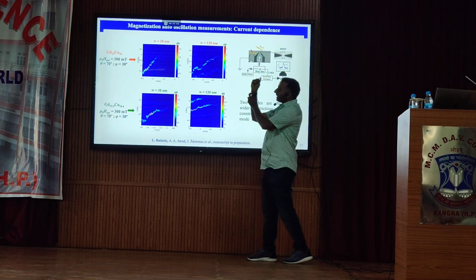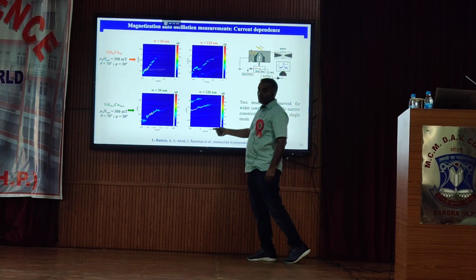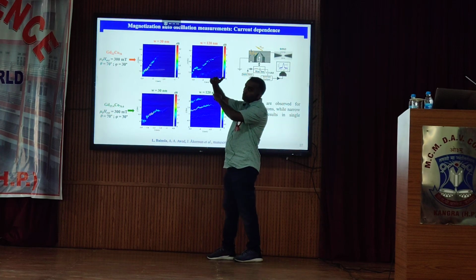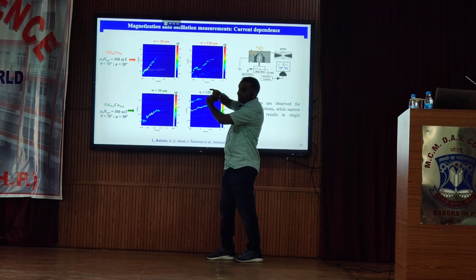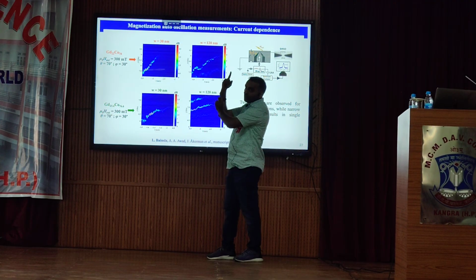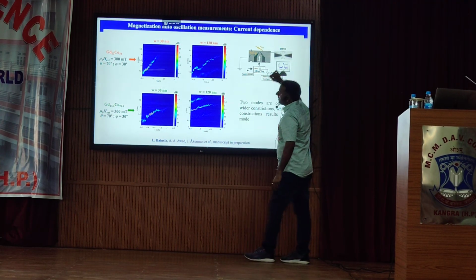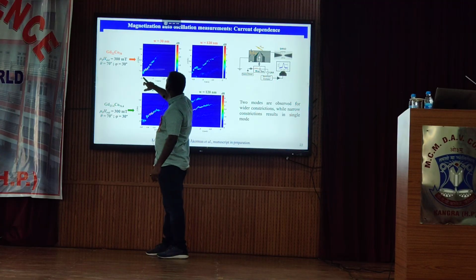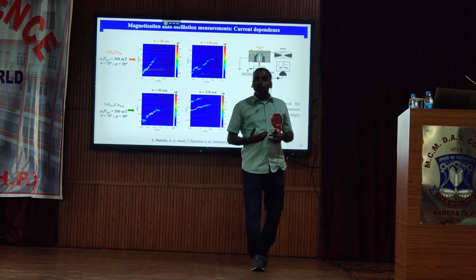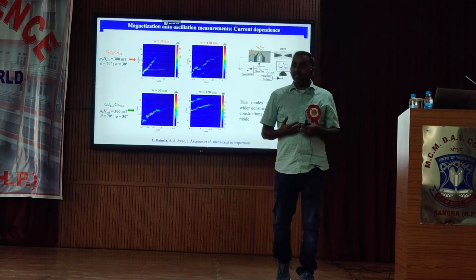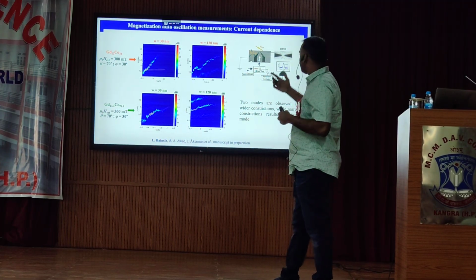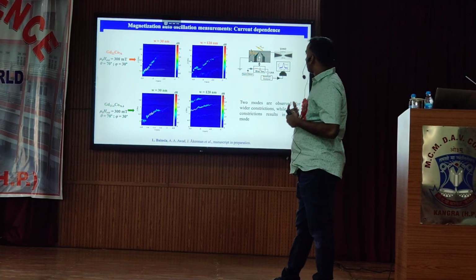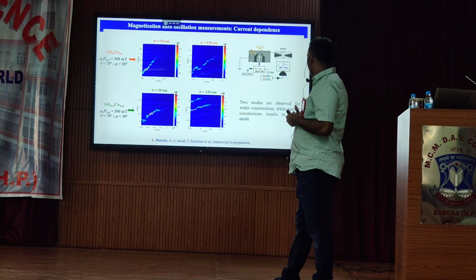So we analyze how the magnetization is precessing when we apply the current. In this kind of sample, where we have platinum and gadolinium cobalt, when we apply the charge current in platinum, how the dynamics in gadolinium cobalt is happening, we measure using this setup with the spectrum analyzer. And as you can see here, we can see the magnetization oscillations in negative polarity of the current for both compositions. This is different from what we observed in spin orbit torque efficiency. In spin orbit torque efficiency, we see a sign reversal for these compositions, but the magnetization oscillations we get in the same polarity of the current. This is quite surprising to us.